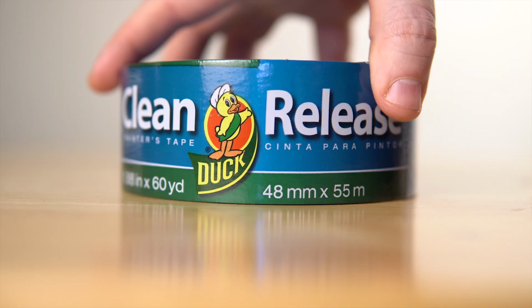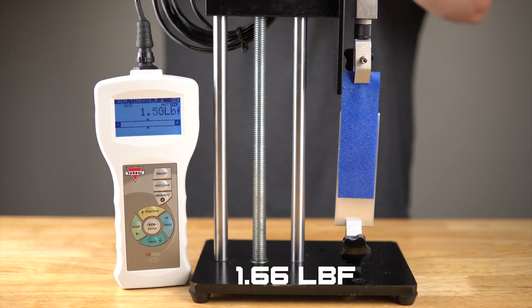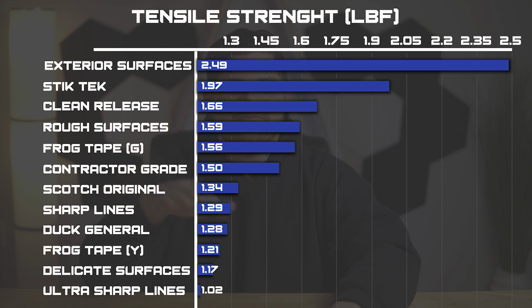So, which tape do we recommend? Well, it depends. If you're on a budget and you have a lot to mask, we recommend you go with the Duck brand Clean Release. It had a high tensile strength with a strong adhesive and was up there in the rankings every time. If sharp lines are absolutely critical or the surface you're painting is rough, then we must recommend the green Frog Tape. There's just no competition.